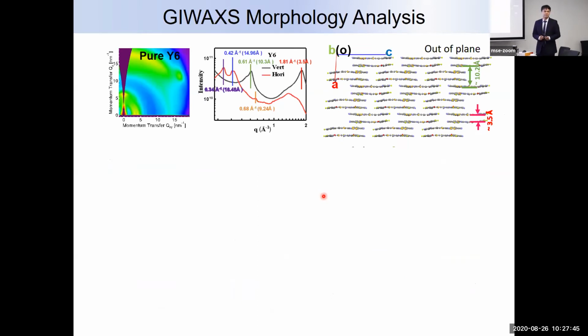So more importantly, now we know the crystal structure. We also need to know whether this crystal structure is preserved in the thin film, okay? A lot of the time, if you process it in a different way, they may not have the same crystal structure in the thin film. And luckily, we did this GIWAXS study, and we find that corresponding to the face-on orientation, we have a very good pi-pi stacking here, and also another characteristic peak, which corresponds to the distance between these 2 dimers. Okay, so they can be observed in the GIWAXS, which means in the pure Y6 thin film, this material is oriented face-on with the substrate.